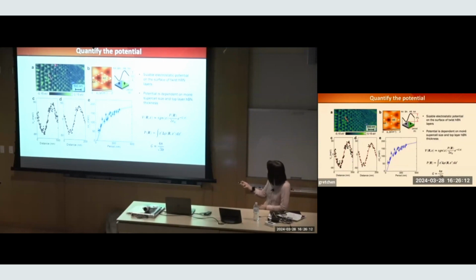But the potential trap is 200. As the supercell gets smaller, we stop at 50 nanometer. That's how our tool is limited. We don't have the most desirable AFM to do this experiment. And this solid curve is not even a fitting, it's a calculation. And we shifted it vertically to fit the data points.